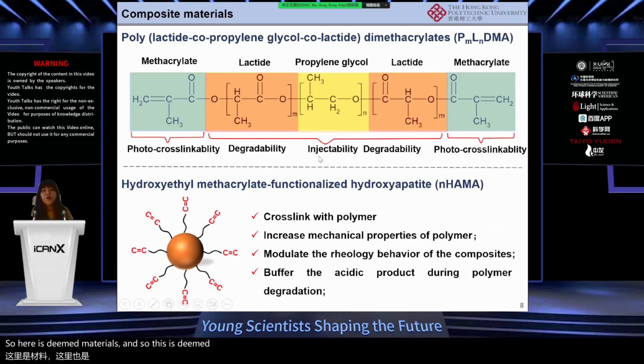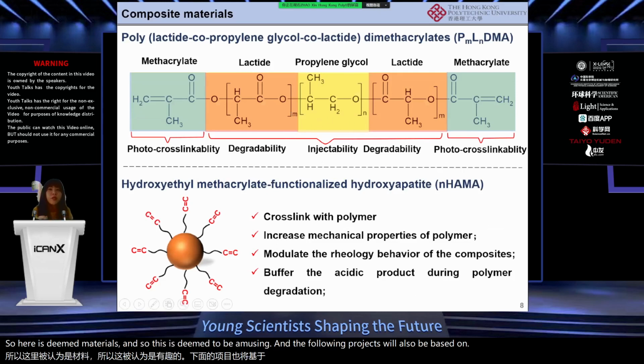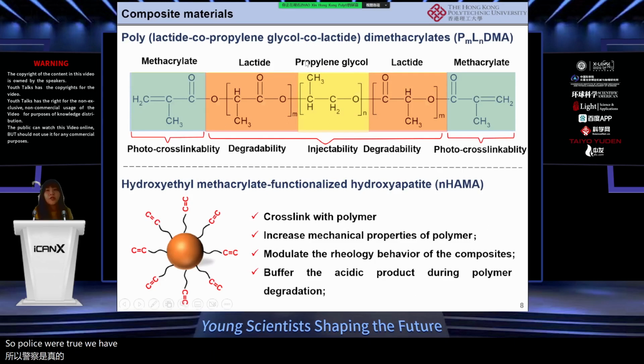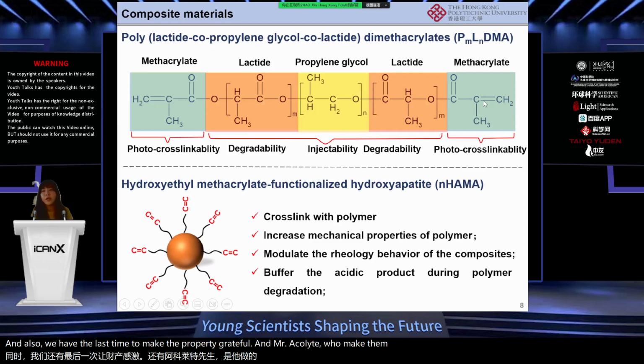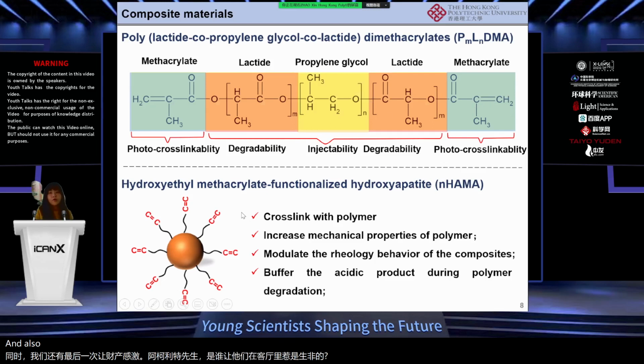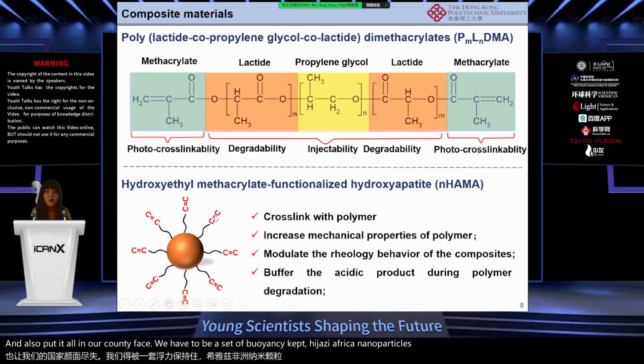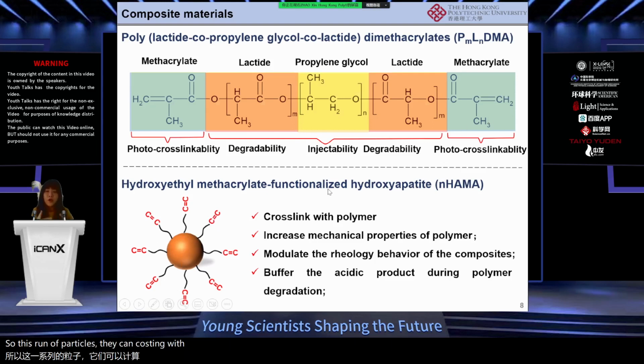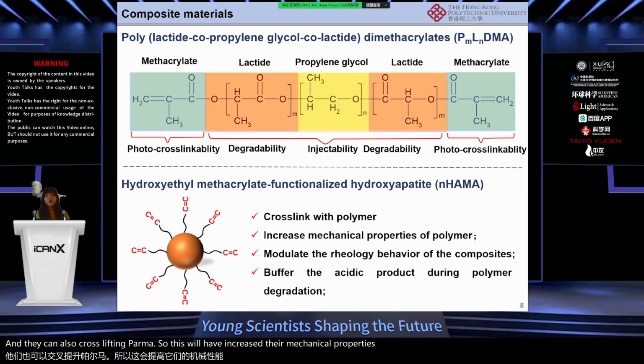Here are the materials we are using, and the following projects will also be based on these materials. For this material, we have propylene glycol to make the polymer injectable, lactide to make the polymer degradable, and methacrylate to make the polymer photocross-linkable. And for the inorganic phase, we have the C=C-capped hydroxyapatite nanoparticles. These nanoparticles can cross-link with themselves, and they can also cross-link with the polymer. This will increase their mechanical properties, and they can also modulate the rheology behavior of the composites, so they can be easier for 3D printing. And when they degrade, they can buffer the acidic products during the polymer degradation.